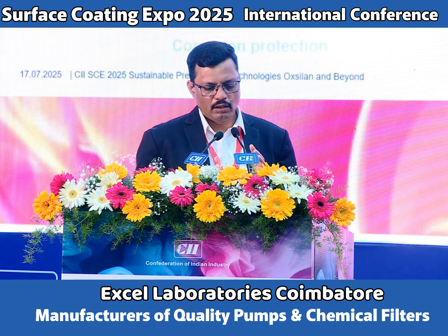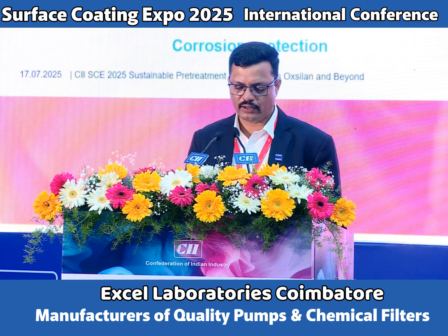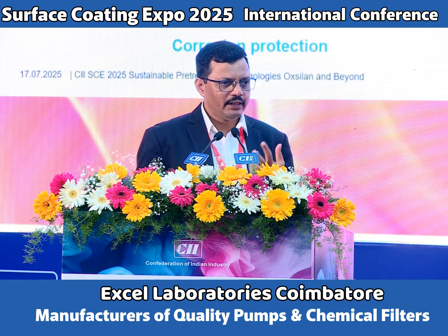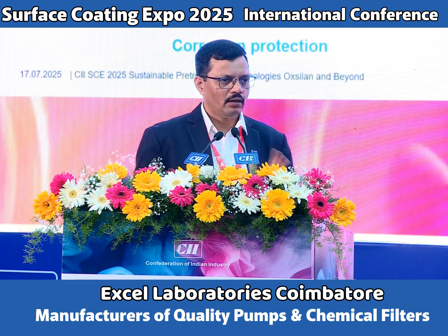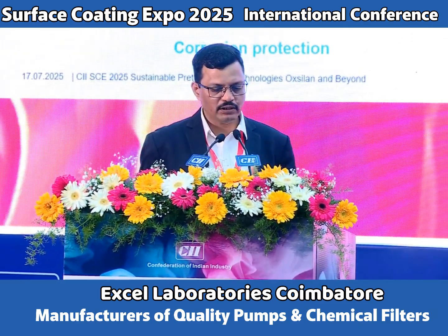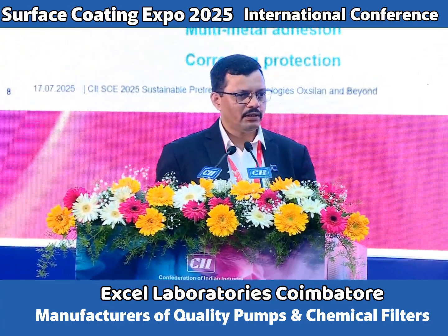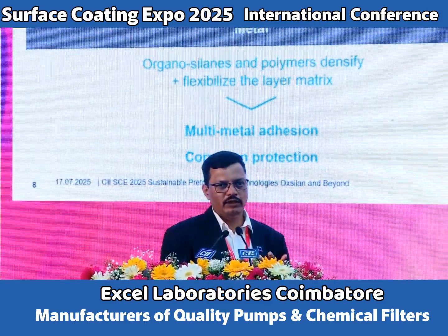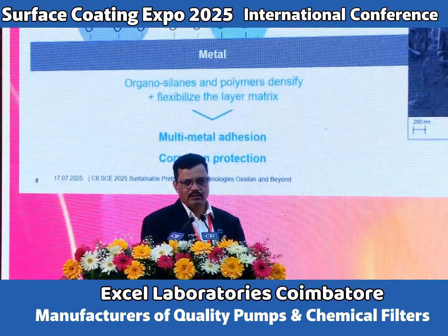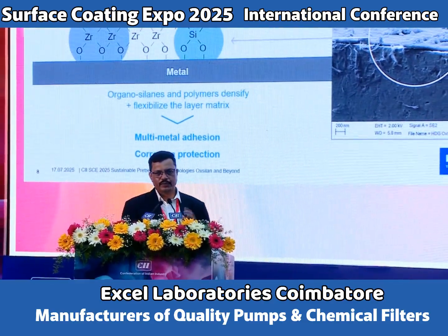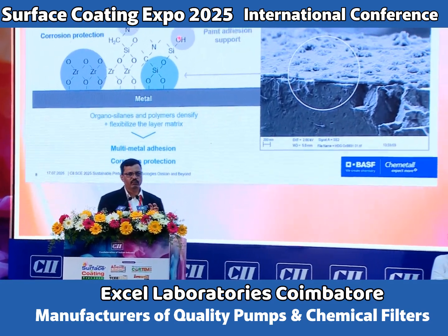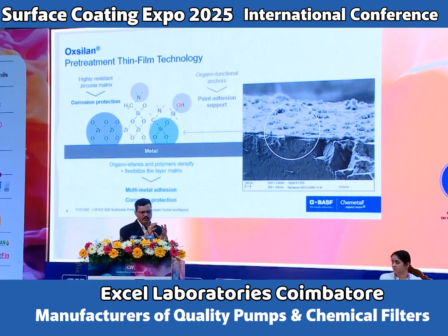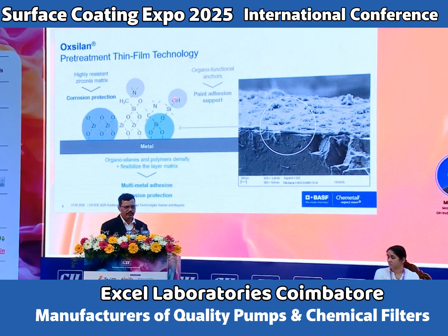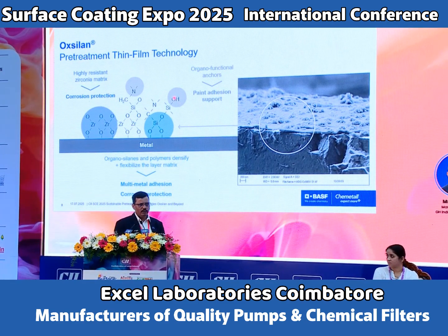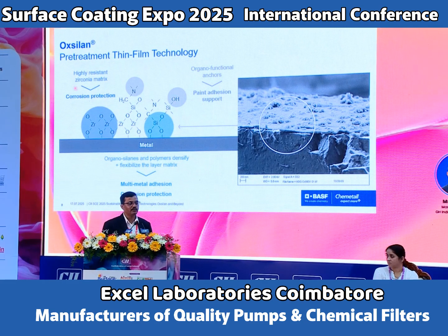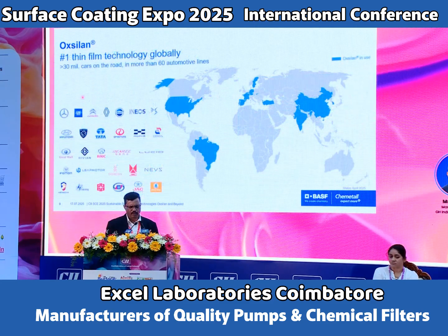Along with this, as I said, we have the organofunctional silane. This organofunctional silane improves the flexibility, and it densifies the complete structure of that conversion coating film. You can see here some of the functional groups like hydroxyl or amine group. These are active in nature, and these functional groups take part in the chemical reaction with the resin system of the paint. Okay. Unlike conventional zinc phosphate, where the adhesion of paint is governed by mechanical forces, here in Oxsilan thin film technology the adhesion of the paint is governed by chemical bonding, and that's why we get better adhesion to the paint substrate, as well as, because of this highly resistant zirconia matrix, superior corrosion protection.